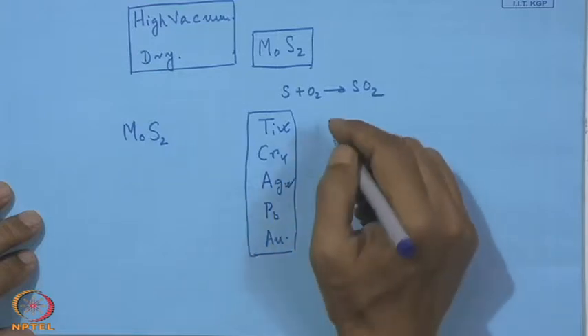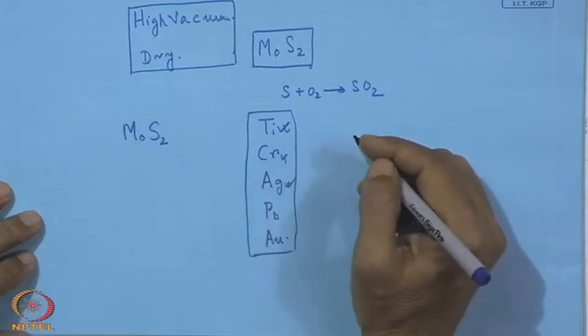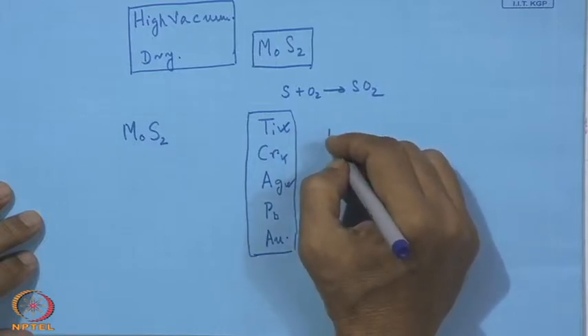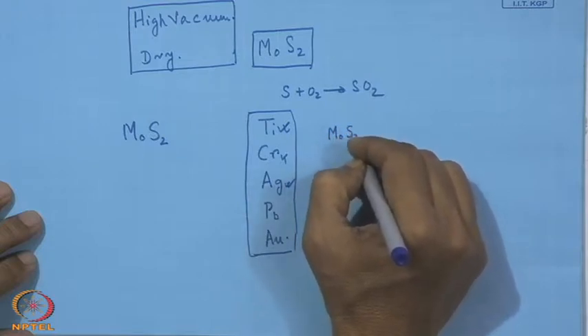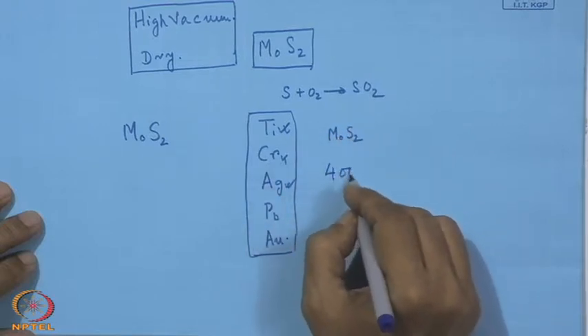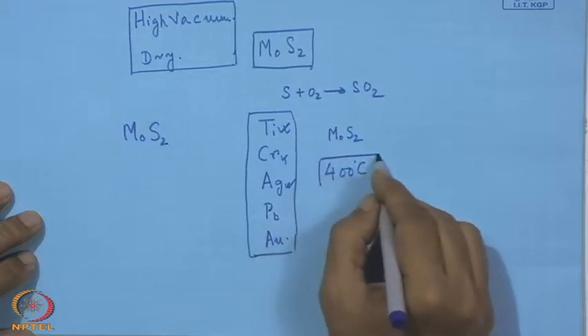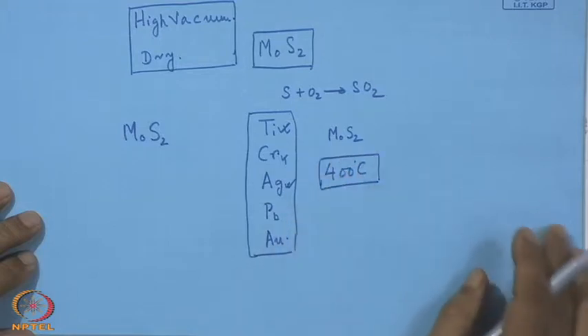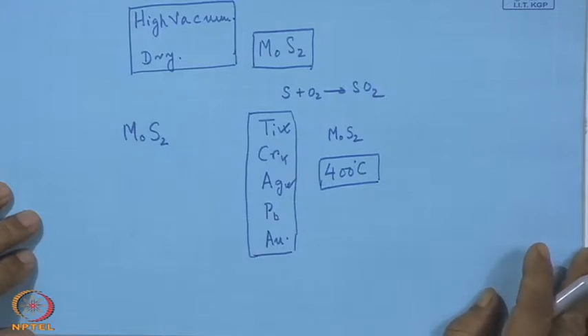We know from research documents that MoS2, in open atmosphere, is stable up to 400 degrees centigrade. So, when the requirement is above 400 degrees centigrade for any application of that component or part, we have seen that the frictional coefficient rises quite fast, and that means that is the end of the service life of the coating. So, this coating is no more useful.